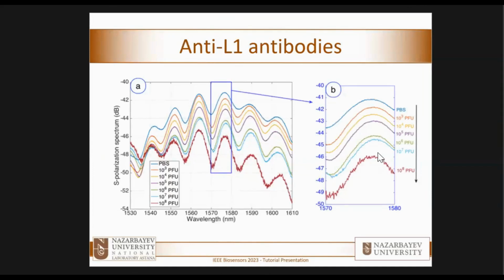So that's how they work. First, this is the one for the L1 protein, the best performing protein that is found on the surface of the vaccinia virus. And yes, we have again the same pattern. So when you actually start from an enriched PBS right here, back into all the virus concentration, you see that there is a quite visible sensitivity. And yes, this is again a random spectrum. So each time the spectrum will look different. So there is a sensitivity that is appreciable quite here, really quite large. Notice that the change that we have going from 1000 to 10 to the power of 8 plaque forming units is quite large. We're talking about 6 dB. That's quite large change of signal.